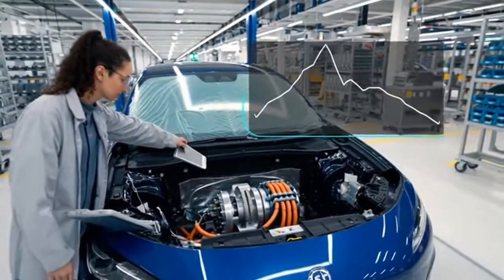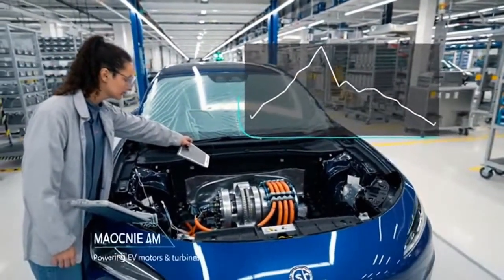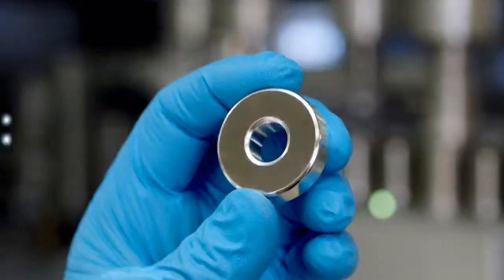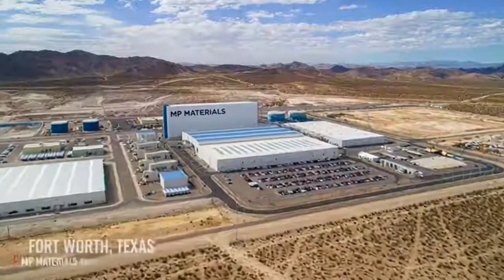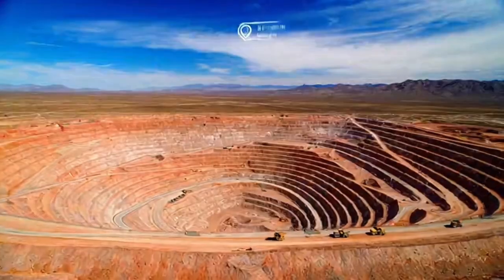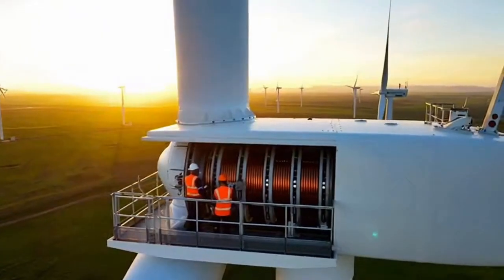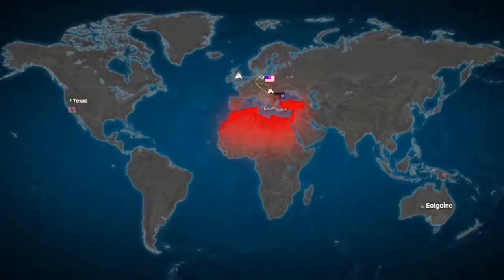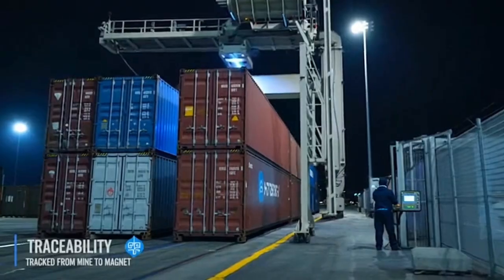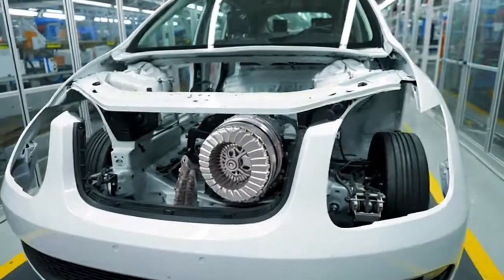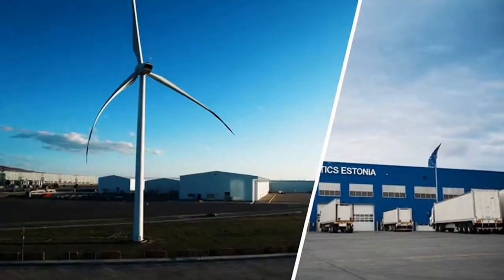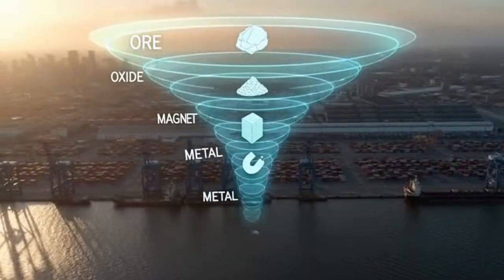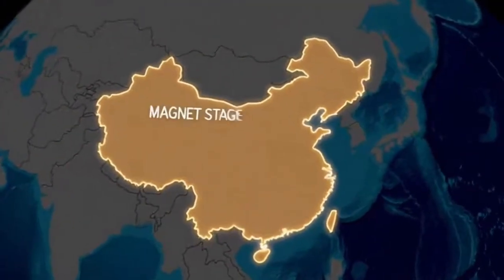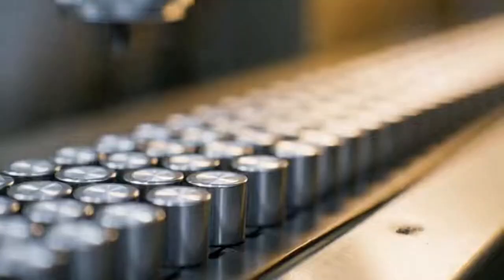Start with ore. If it's bastnasite, you mine it and crush it, then put it through flotation, where bubbles and surfactants carry the rare earth minerals to a froth and leave the waste rock behind. Now you have a concentrate, still messy. You roast it to drive off the pesky carbonates and fluorides in a controlled way, then leach it with acid. If your ore is monazite, you have to be more careful: roast it to crack the tough phosphate lattice, leach it, and have a parallel plan for those thorium-bearing residues that will outlive everyone in the marketing department.